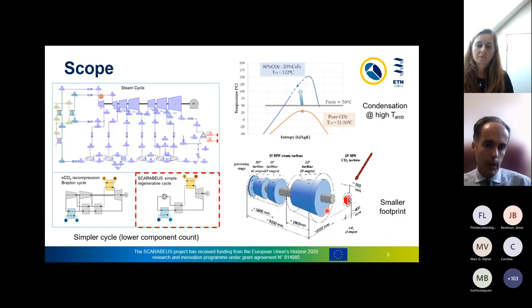As far as scope, you can see here that we are working in different areas. So where I'm now marking with my pointer, the key feature of the project is, let's say, supercritical CO2 systems are nice and cycles are nice as long as you can get close to the critical point and therefore exploit the very high density of the working fluid in the compression process. Now, if you're in a CSP power plant, it is very likely that you cannot get to those low temperatures, and therefore it is difficult to take advantage of those features.